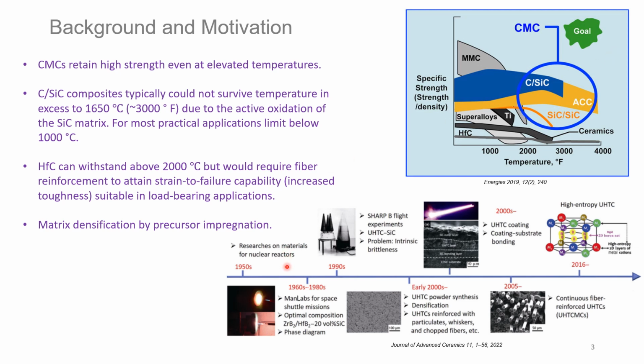The earliest research on this ultra-high temperature ceramics, specifically hafnium boride and zirconium boride, can be traced back to the 1950s, where they were used as nuclear reactor materials because of their excellent high temperature corrosion resistance. Then in the 1960s to 1980s, Air Force Research Lab explored the potential of ultra-high temperature ceramic materials for anti-oxidation and ablation resistance. However, by the end of the 1990s and the beginning of the early 2000s, the intrinsic brittleness of these materials was discovered during a flight demonstration.